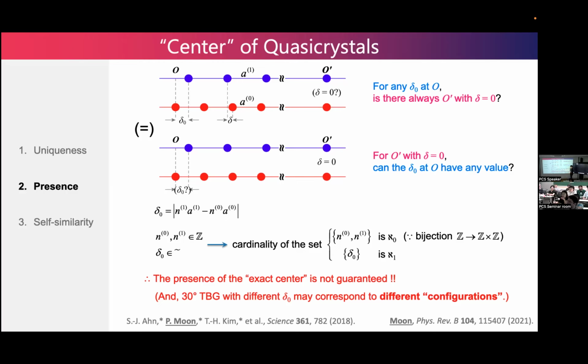In an infinite quasicrystal, if you have a small quasicrystal, just shifting two layers, I am assuming that I can produce any configuration, just shifting one unit cell. Yeah, you can assume that, but when you go to infinite, it seems to me that all delta appear. Yeah, that's our first understanding or assumption. And we encountered this also in the dual space tight binding model, but the conclusion is that a single twisted bilayer graphene quasicrystal will not show every local configuration.